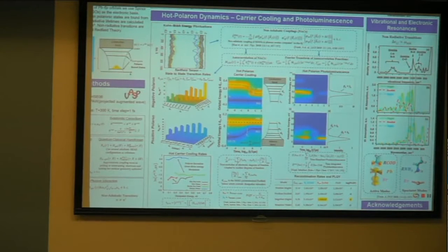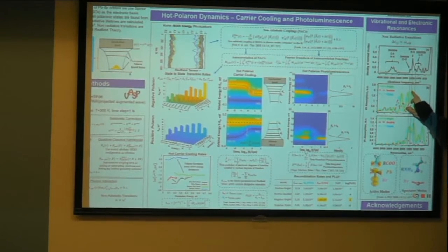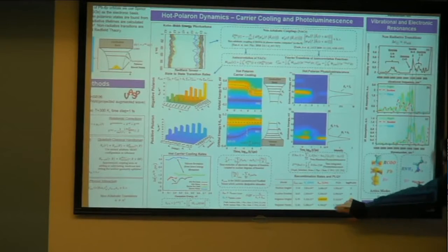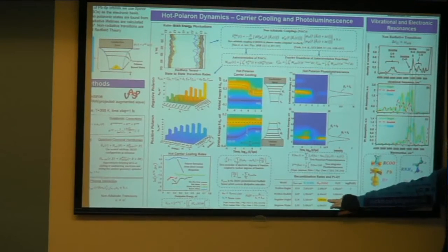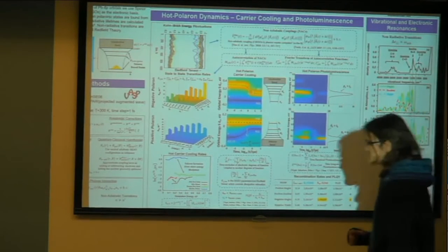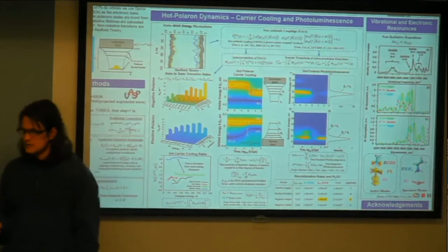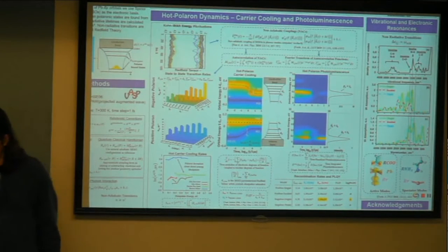So this resonance doesn't actually provide anything to the non-radiative decay, whereas for this triplet, it's in resonance with the stretching group on the surface. So that's how we explain this two-order magnitude difference. One's in resonance while the other is in a spectator mode, so it has a longer lifetime. And so that's essentially the story for the first part of this research that's been published in JPCC.